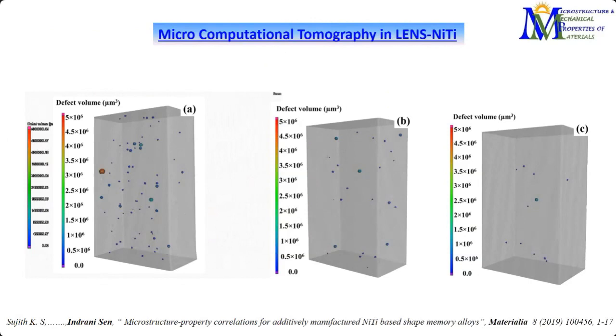On the other hand, for other implants like bone implants, porosity is often desired. Biomedical applications often require porosities of certain percentages, and for that, additive manufacturing is of great help because we can control the porosities and even the structures and positions according to our need. For this particular study, as we increase the laser density, the compaction is much better, and we end up with lesser amounts of porosities.